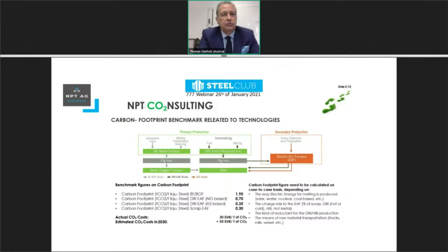What are the actual costs of the CO2? Because this is very important to understand where the pressure is coming from. Actually, the CO2 cost per ton of CO2 as a certificate which is burdened to the steel plant is in the range of 30 euro per ton. And it's estimated to reach a value of plus 50 euro in 2030 by the rules at the moment applied by the European Commission. What does it mean?